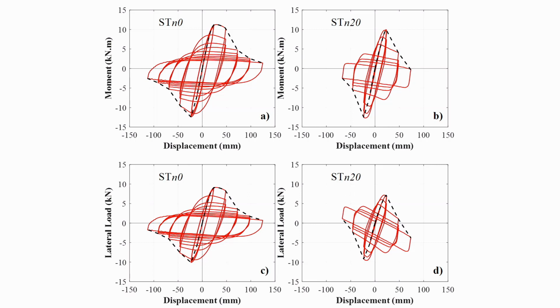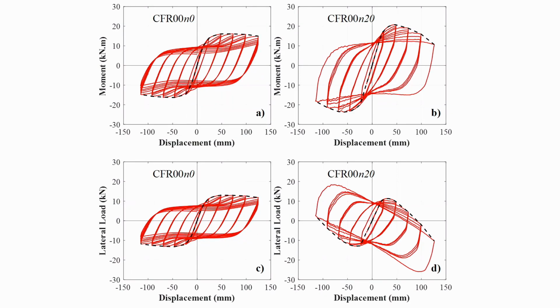And then I'm also plotting at the bottom there the lateral load against the displacement results. And the lateral load was taken as the effective lateral load at the top of the member, plotted against the top displacement. So these are the results for the hollow steel tubes. N0 is the zero axial load level, and N20 is when they had an axial load level about 20% of the cross-section capacity. And then these are the results for the CFR00 infilled specimens.